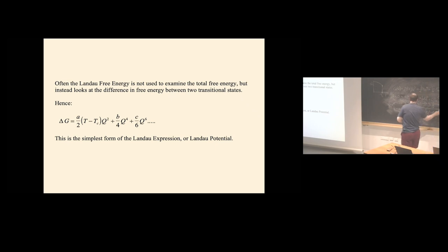So, without further ado, let's go to the second order phase transition. We've looked at what happens when B is negative. Now let's consider when B is positive. When B is positive, you're onto a winner, because you've got a prefactor here which is initially positive but then goes negative below TC because of the toggle here. You've got something here which is always positive, and so even when this is negative, it can counteract this positive term and give you a double well potential which is physically meaningful.